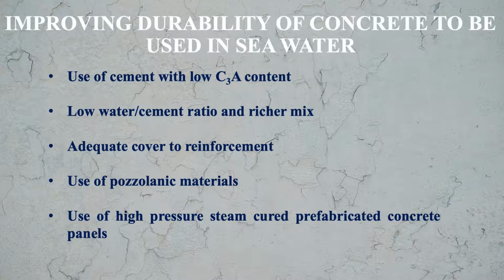So let us see how we can improve the durability of concrete which is to be used in seawater. We can do it by use of cement with low C3A content, low water cement ratio and richer mix. Adequate cover to reinforcement should be given. Then we can use pozzolanic materials. Also we can use high pressure steam curing for the prefabricated concrete panels. So by adopting these methods, we can improve the durability of concrete which is to be used in seawater.